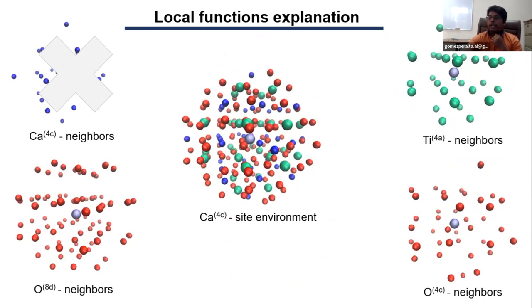And we can distinguish the neighbor atoms depending on the crystallographic site that they occupy. In the slide, I show you the neighborhood of the calcium located in 4c sites, and we can split the neighbor atoms according to the sites that they occupy. For example, the titanium atoms occupy 4a Wyckoff site, and something similar happens with the oxygen that occupy sites labeled as 8d and 4c.